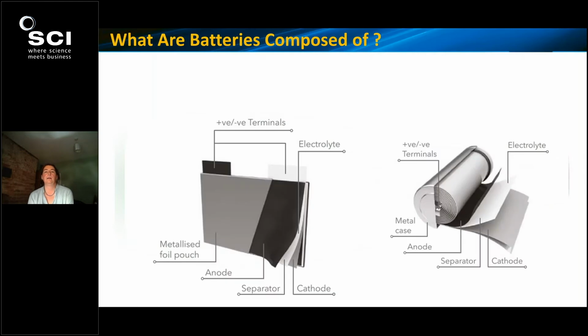When we look inside these cells, the configuration of how the electrodes are stacked is very different. In the pouch cell, we can see a sort of lasagna-type effect where the anodes and the cathodes are stacked and separated by what is called a separator, which is an organic porous film that stops the electrodes touching and electrically short-circuiting, whereas in the image on the right, the layers are wound into an Archimedean spiral. So they are very different.